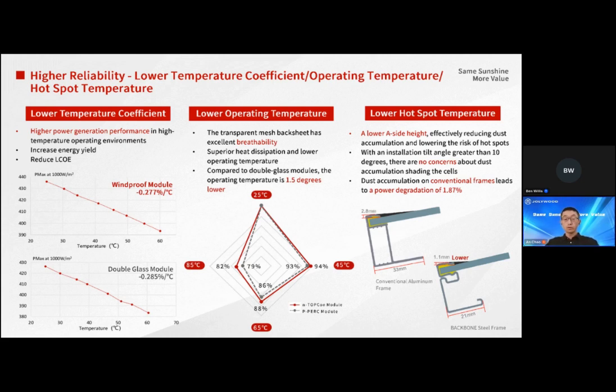The windproof module also has good performance regarding thermal loss, with a lower temperature coefficient of minus 0.277% per degree Celsius, which means less power loss during high temperature operating conditions. Additionally, the transparent mesh backsheet promotes better heat dissipation, reducing the operating temperature by 1.5 degrees Celsius compared to double glass modules, contributed by the design of the frame. A lower A-side height, effectively reducing dust accumulation and lowering the risk of hot spots.